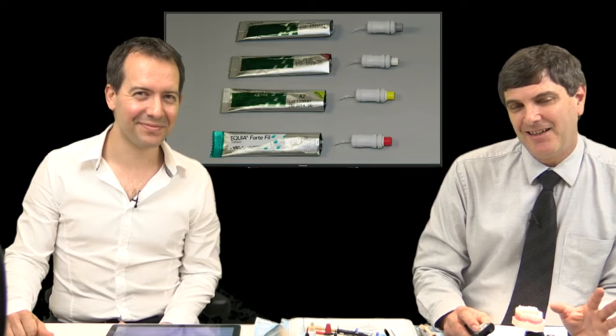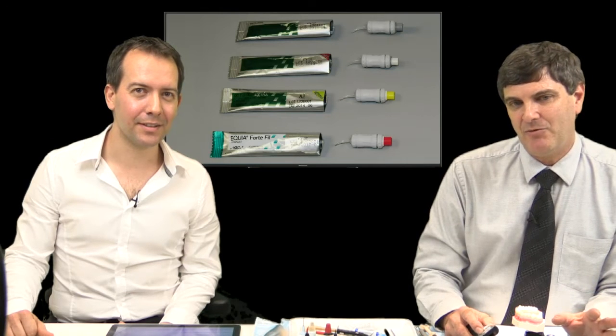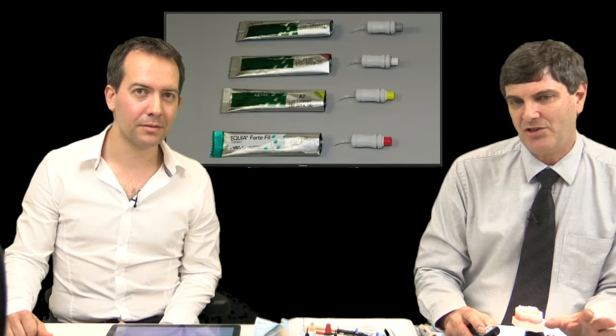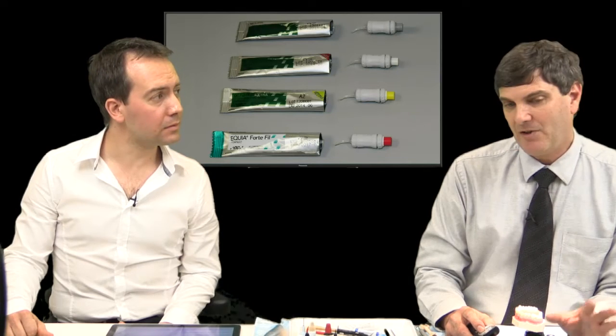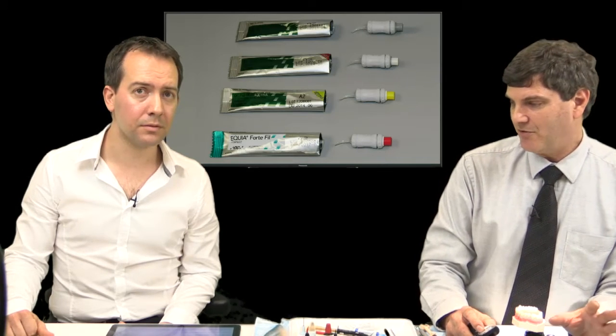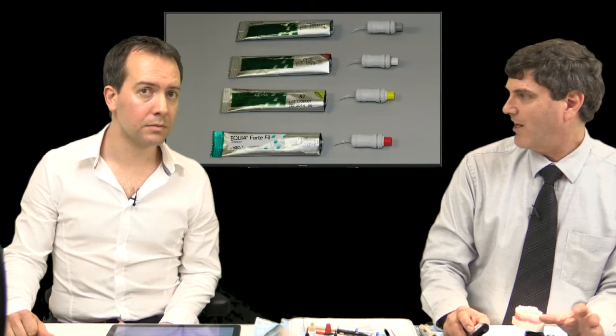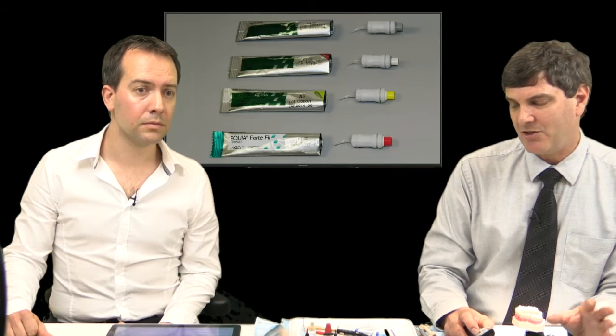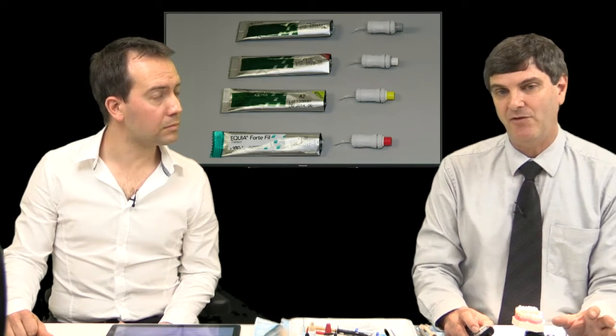But what happened here is that it was recognised that Fuji 9 Extra was actually highly soluble. One of the nice things about Fuji 9 Extra is it's got good aesthetics. It's very translucent, and it's got a highly reactive glass, which means it sets really quickly. Problem is with that highly reactive glass, it's also quite acid soluble. So I think the movement to Equia Forte Fill was an opportunity to get something which is a little bit less soluble and also have good fluoride release.